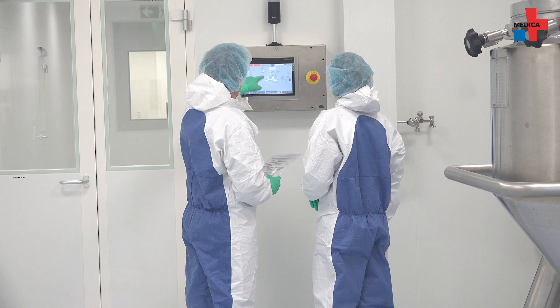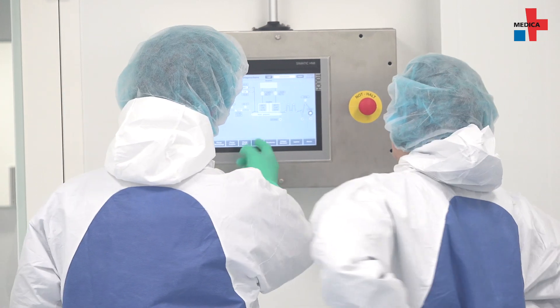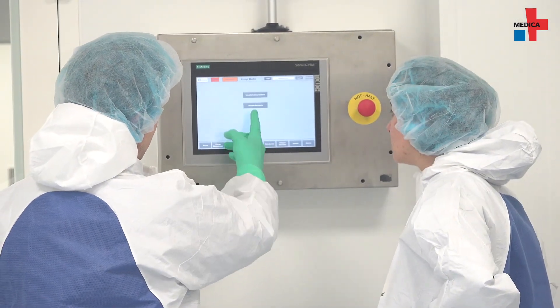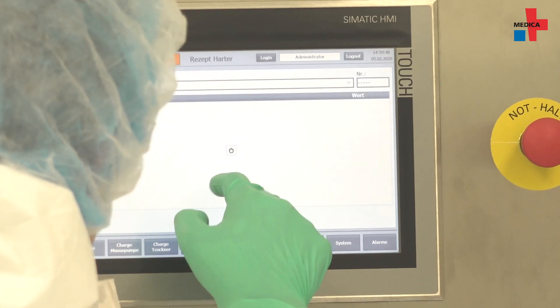We take the lower layer of the bovine skin, while the top layer goes to the leather industry. The lower layer is chemically cleaned using a basic alkaline solution and treatment process, leaving us with a piece of white collagen. It is subsequently mechanically crushed and used to make a kind of dough we call collagen mass. We then extrude this collagen mass to create our membranes and collagen fleece.